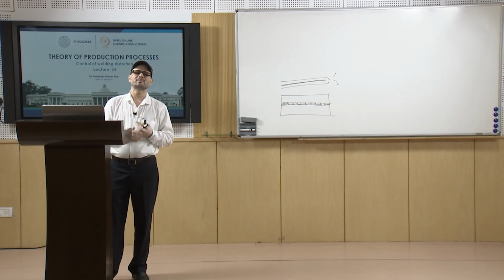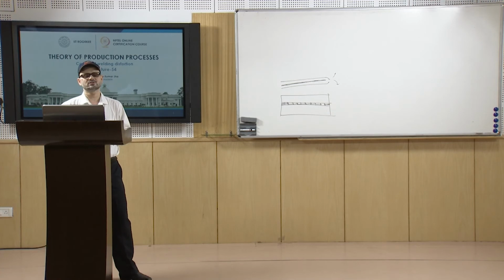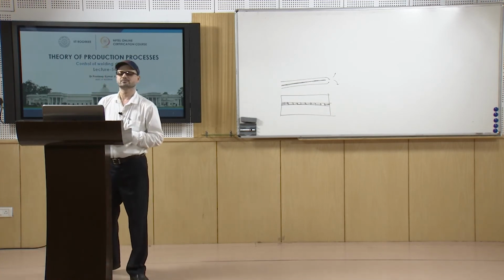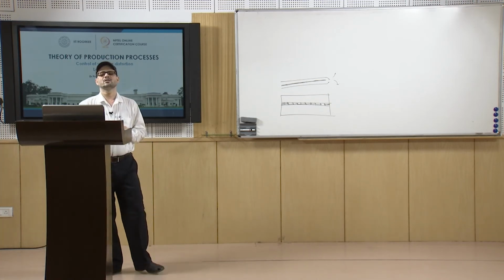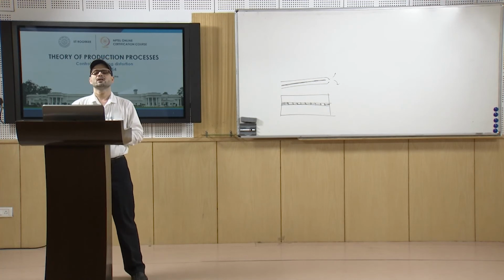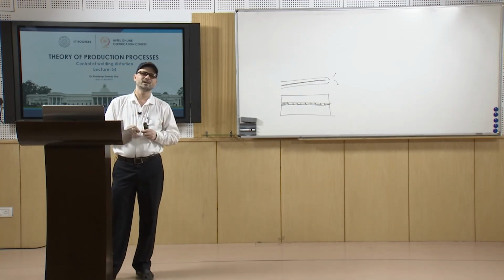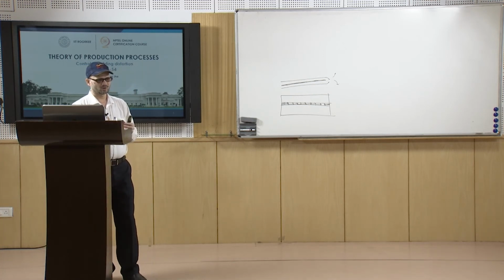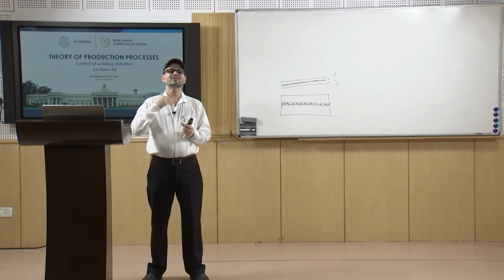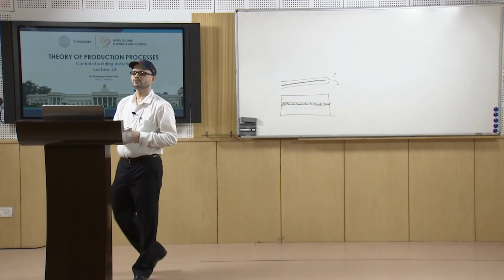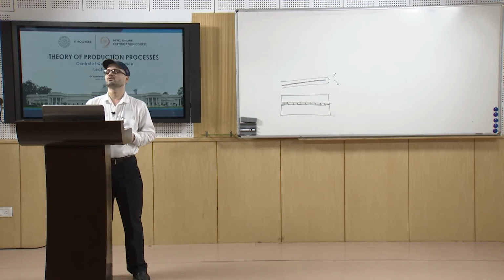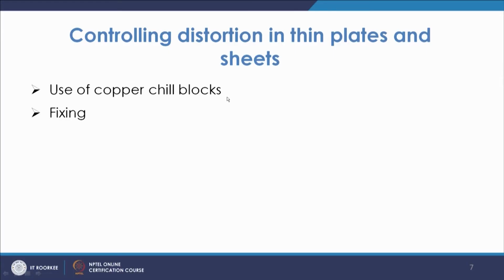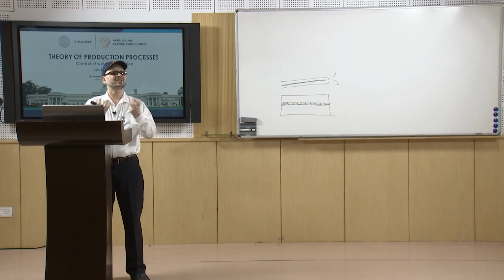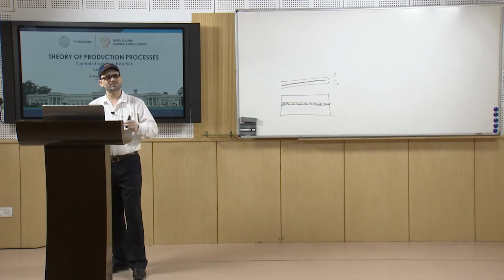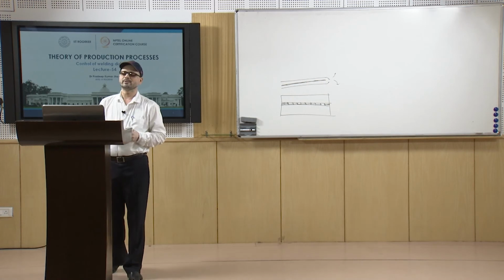Now, many a times we also put a backing strip in case of butt welds. So, that is another way of reducing the distortion. Now, we will discuss distortion control in thin plates and sheets. When we weld thin plates and sheets, distortion takes place because of the intense heat which is applied. So, normally we use copper chill blocks under the joints, so that most of the heat is extracted by these copper chill blocks. So, the chances of warpage or buckling because of the intense heat content will be reduced.